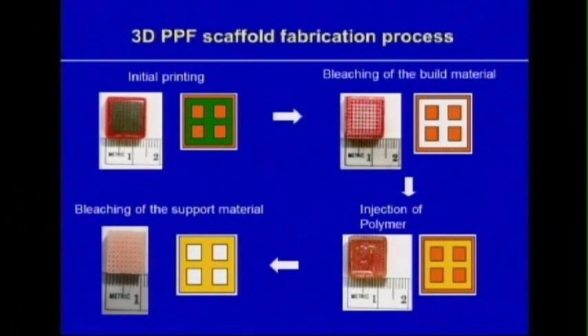We then take that porous thing that's wax and we flow the monomer in it, but this time instead of using photo initiation, we use redox initiation, and we put both an initiator and an accelerator in with the flowing monomer. It hardens within the pores, and once these polymers harden and cross-link, most of them don't melt until well over 150, 200 C. And so we simply then take that thing and raise the temperature a little above 65. The wax goes out. And we use this when we use a new material, because then we have a porous scaffold of any material that we can polymerize via a redox initiation. So those are the 2 we use. We have also fused deposition modeling and electrospinning that we use in the lab, but these are our 2 workhorses, these 2 to make scaffolds.